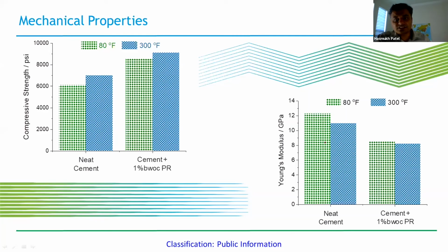The Young's modulus of neat cement is ranging from 11 to 12 gigapascal, and it reduced to about 8 to 7 gigapascal for cement with 1 weight% polyrotaxane. So what does it generally suggest? It suggests that we are not compromising compressive strength, and at the same time we are able to reduce the Young's modulus. So basically, we are introducing toughness into the cement matrix by using the polyrotaxane. That is a very encouraging result that provides an idea of how polyrotaxane, or molecular machine type of polymeric additives, actually distribute the stresses within the cement matrix and provide such fantastic mechanical properties for oil well cements, which can actually help in extending the lifespan of the oil and gas wells.